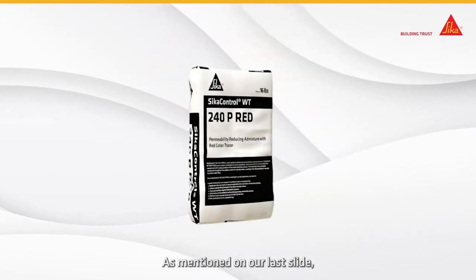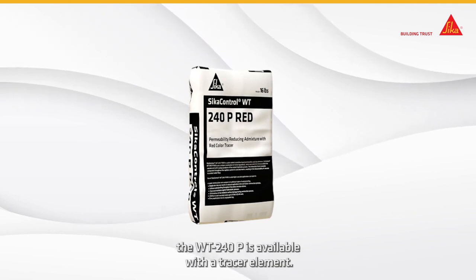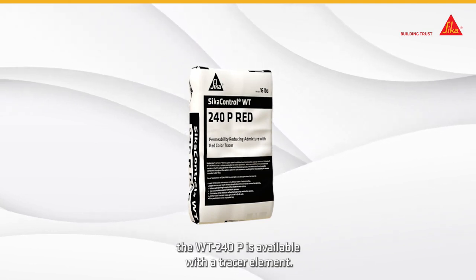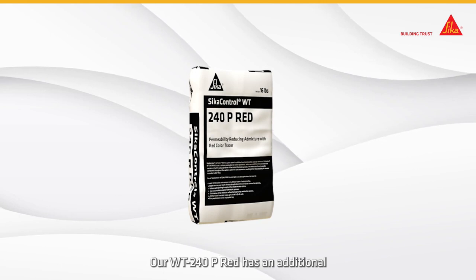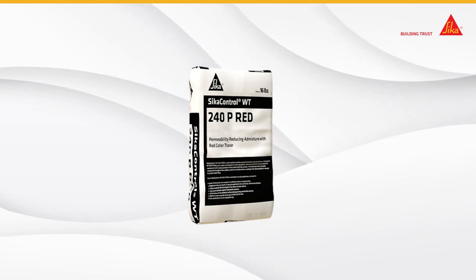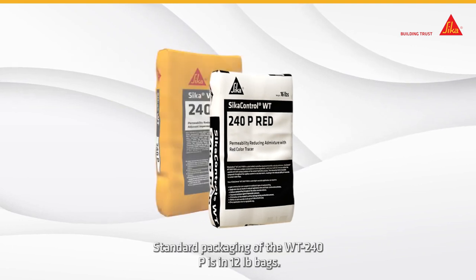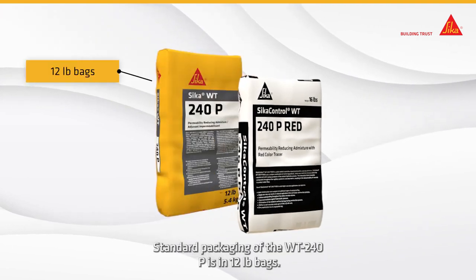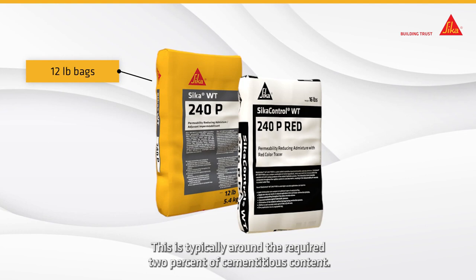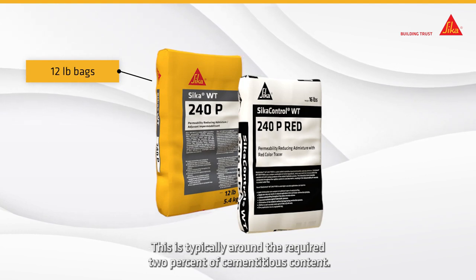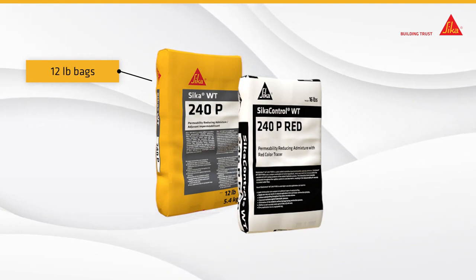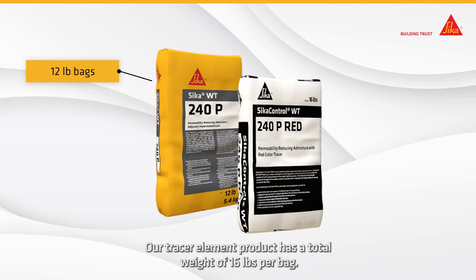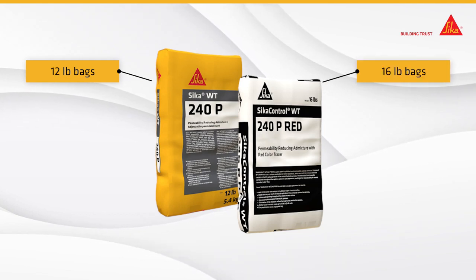As mentioned on our last slide, the WT-240P is available with a tracer element. Our WT-240P Red has an additional 4 pounds of red color added to the mix. Standard packaging of the WT-240P is in 12-pound bags. This is typically around the required 2% of cementitious content. Our tracer element product has a total weight of 16 pounds per bag.